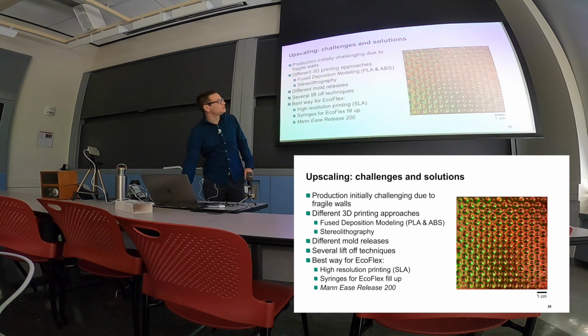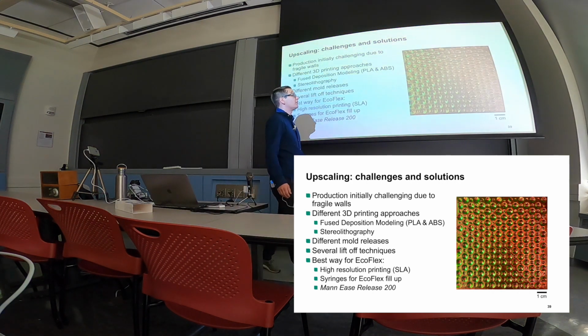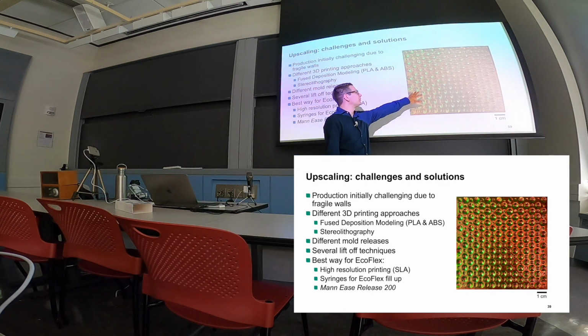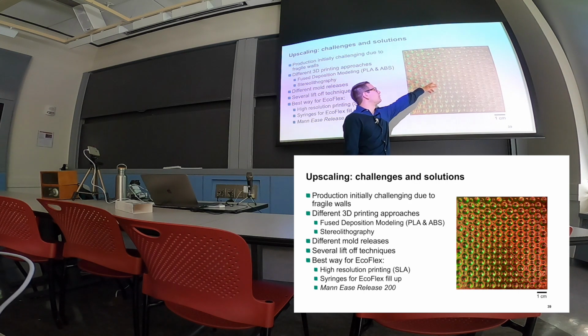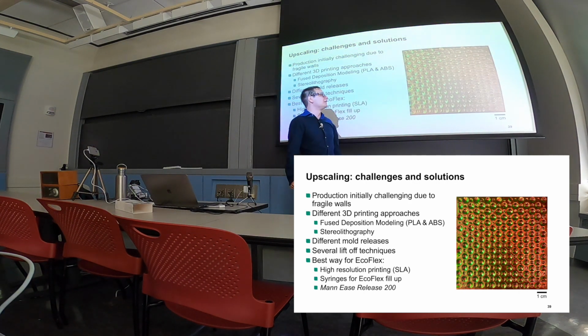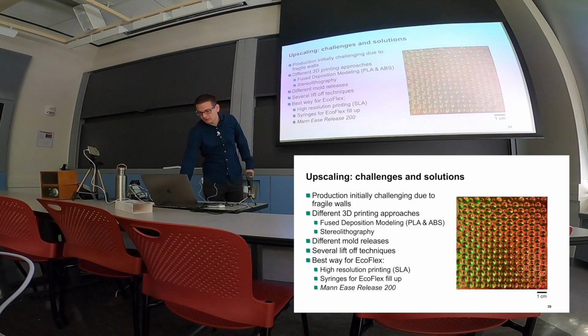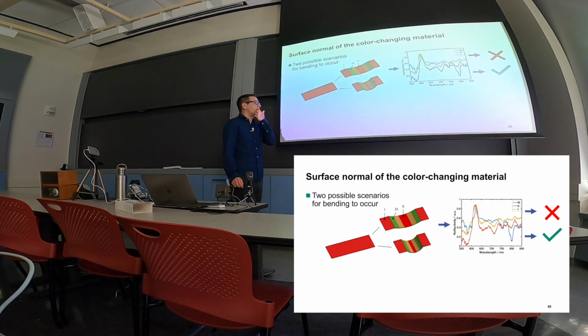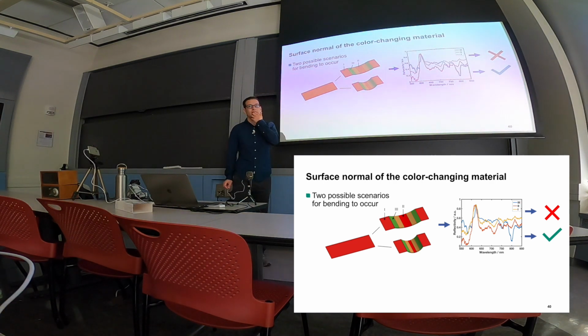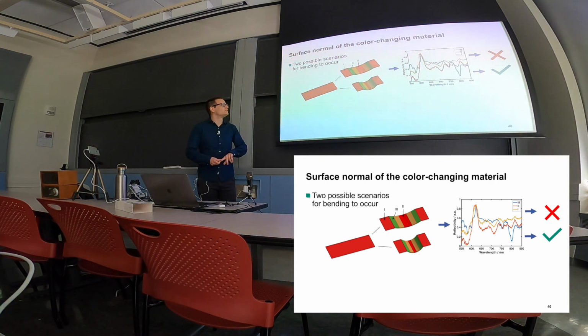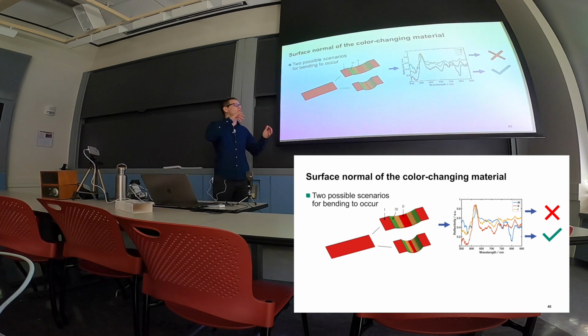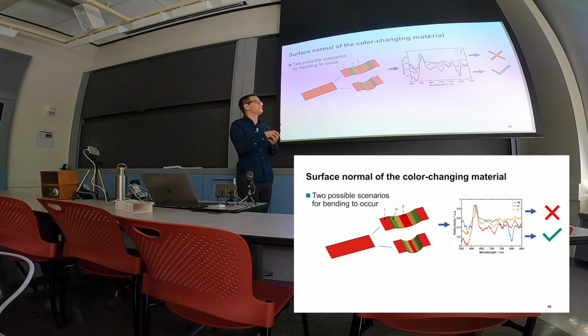And once I had this huge network that we can see over here, we can already see that there are also different colors occurring. However, I could shift around the surface that we see over here, for example the red points in the middle of the cell or on the edge of the cell, or the green points at the walls of the cell. And when shifting that around, I was always able to see red color for each point on the surface. And that meant there is basically only one way which could happen when the cell is sucked in by the vacuum inside of those cells.